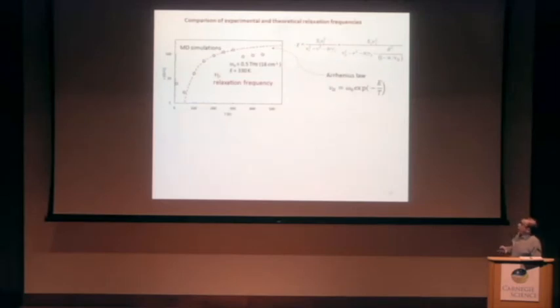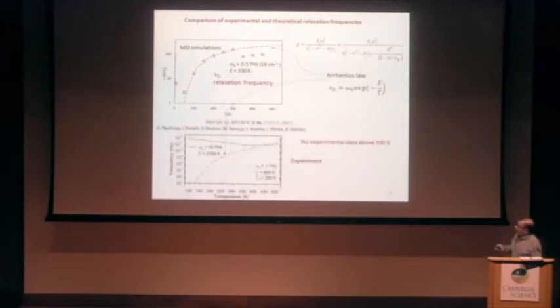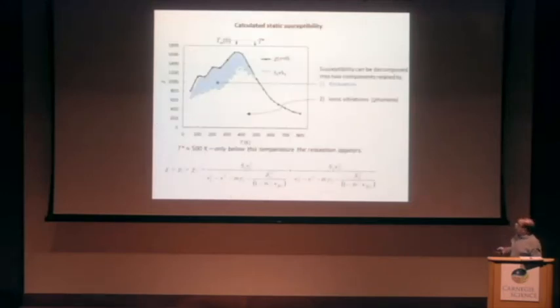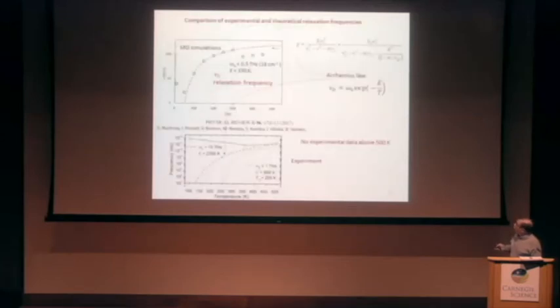And what about the relation between experiment and calculations concerning the relaxation, at low frequencies? This is the calculated relaxation frequency. It follows the Arrhenius law with the parameters shown. And if we compare this with experiment, you have already seen this figure in the previous talk, we can see they found experimentally also one of the modes follows the Arrhenius law. The parameters are a little bit different, which is understandable because we study different frequency intervals. And what is important, there is no experimental data above 500 K. It's very hard to measure.